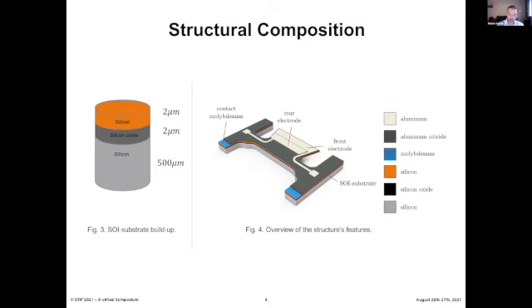And when we apply a harmonic electrical signal, we can create a harmonic electrical excitation. And the aluminum layer is divided into two electrodes, here shown as front electrode and rear electrode. And they can be contacted separately with such pads here. And the molybdenum electrode is used as ground or reference electrode, and it's not divided like the aluminum electrode.